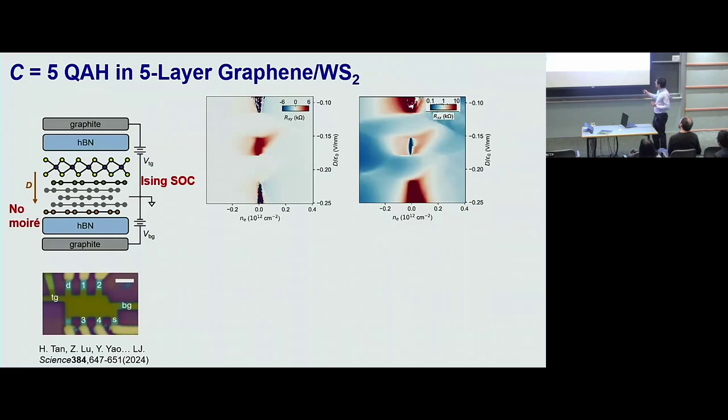What's interesting is, in part of the phase diagram that's located at the charge neutrality, zero charge density, and a range of gate displacement field, you suddenly have a lot of very well-defined anomalous Hall signal, a few kilo-ohm level. At the same time, your longitudinal resistance literally just vanishes, okay? It feels like something topological there.